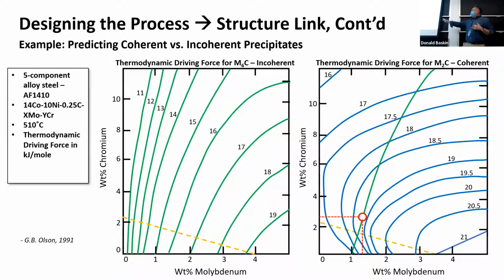Okay, so here we've got these two graphs. One of these is a contour plot for M2C carbides. That's this one here in blue, and then the green one is the driving force for the M6C. Okay, this yellow dotted line right here, those are the correct stoichiometric ratio for the material, so that these are the compositions you can actually get. You can mix these different amounts of these atoms together into the steel, and you can get something along this line. Right? You can't really deviate from this line. You really have to be on this line because of stoichiometric reasons.